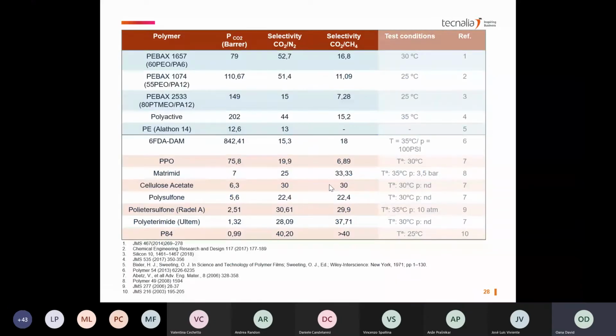So here I listed a few materials. In the upper part, we have all this PEBAX type chemistry, like polyether block amide chemistry, and polyactive. It's also a block copolymer. So these ones, so far, cannot be spun into monolithic hollow fibers. Some of them have good carbon dioxide nitrogen selectivity, and this is intrinsic permeability in barrer, so they can be transformed into commercial membranes by dip coating on porous